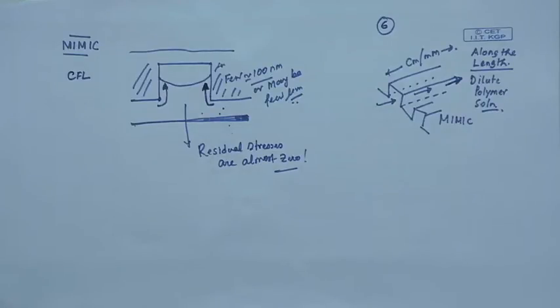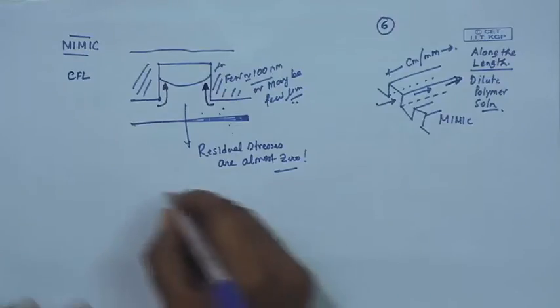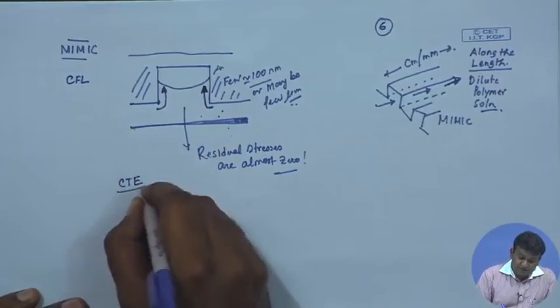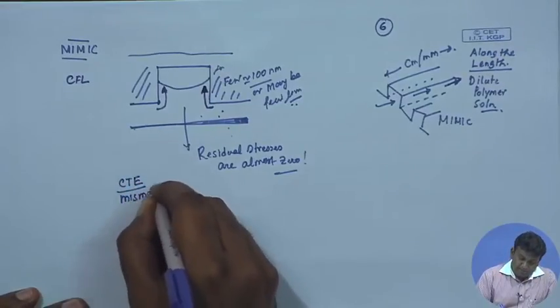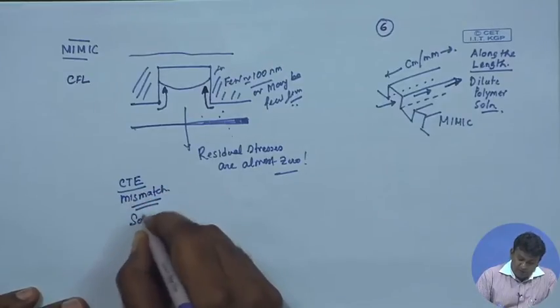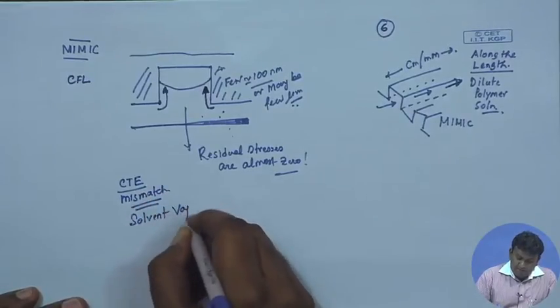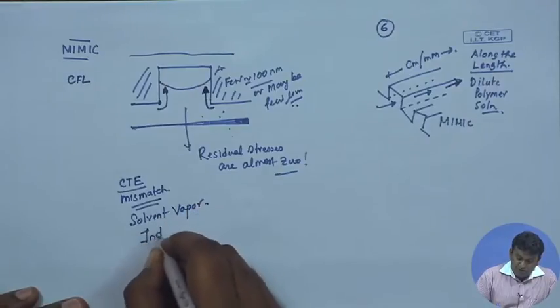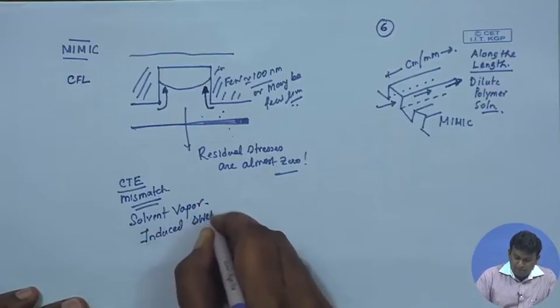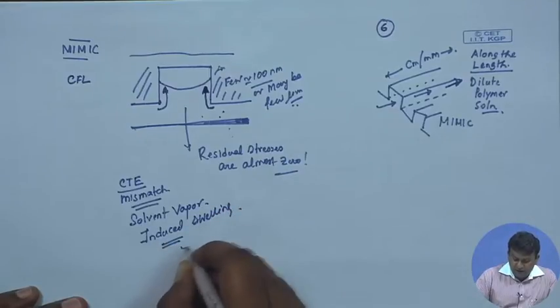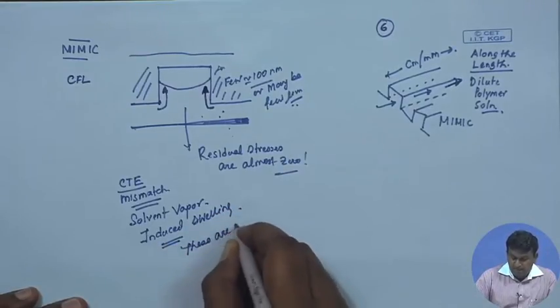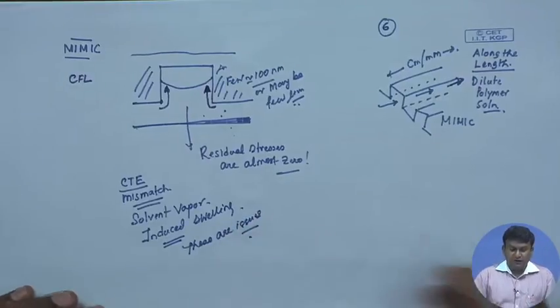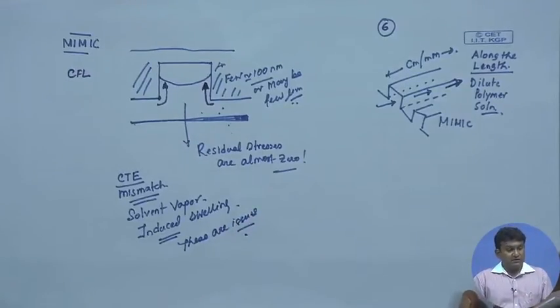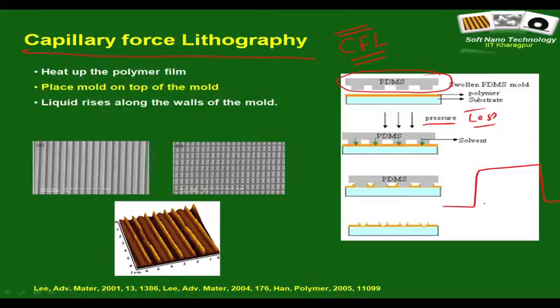Of course, there are issues, as I mentioned, that you need to liquefy the film. So, either you need solvent uptake or you need thermal cycling. Therefore, the coefficient of thermal expansion mismatch or solvent vapor induced swelling are important issues, but there are many advantages that CFL offers, and CFL has become a very popular nano patterning technique.